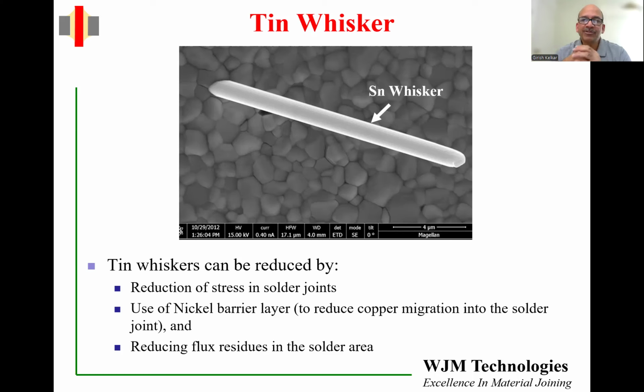When you look at a solder connection, it is actually quite complex. It has the FR4, let's say it's on a circuit board. We have the FR4 base, which has a different thermal expansion coefficient. The copper trace has a different CTE. The solder itself has a different CTE, and the electronic component, which often is made of a ceramic of sorts, will have a different CTE. So when all of these components are at a soldering temperature and then cool down at different rates and with different expansion coefficients, the solder, even though it looks nice and clean, can have a lot of stress in that joint. So one of the things you have to do is reduce the stress with more finesse and control of the cooling rate as it comes down to room temperature.